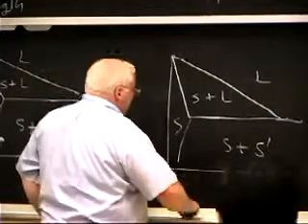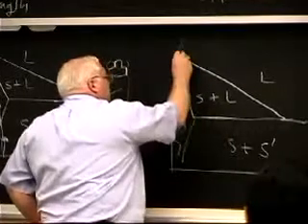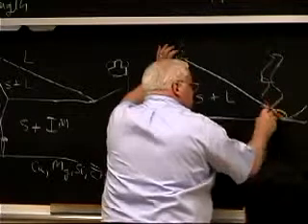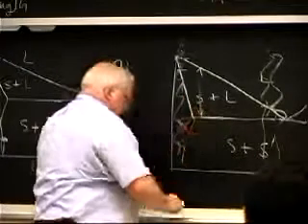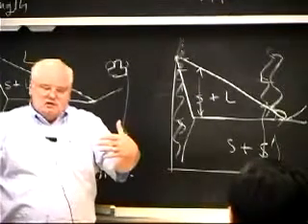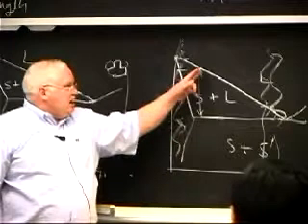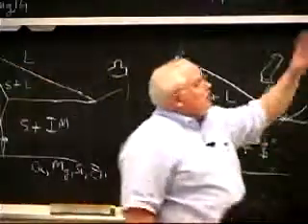But the problem is, what happens in aluminum alloys, I can weld the alloys that exist over here, because the freezing range is fairly narrow on cooling down. I can weld the alloys that exist over here because the freezing range in here is fairly narrow. Here I have a huge freezing range, and these will crack as I try to solidify them, because if I make a fusion weld and the thing's starting to solidify, I've got a whole range of temperatures, but I have to absorb this much thermal strain, delta T times the 6% volume expansion, bigger delta T here than over here or over here.